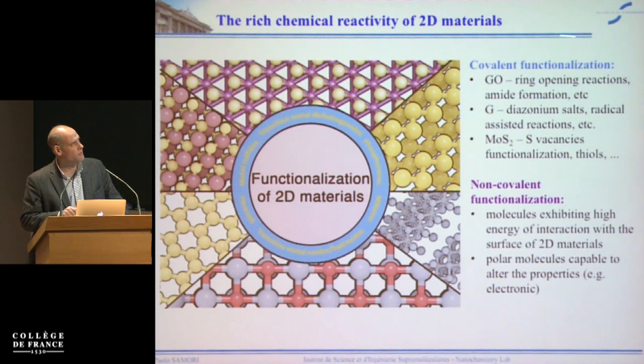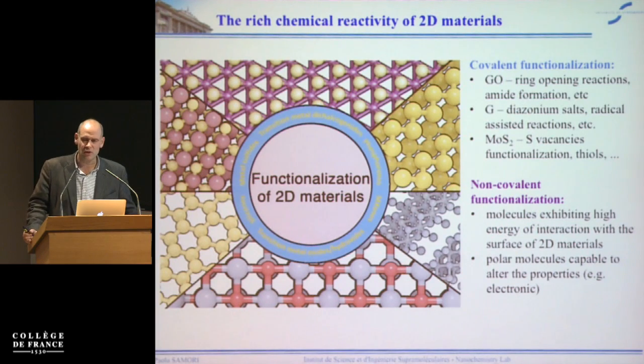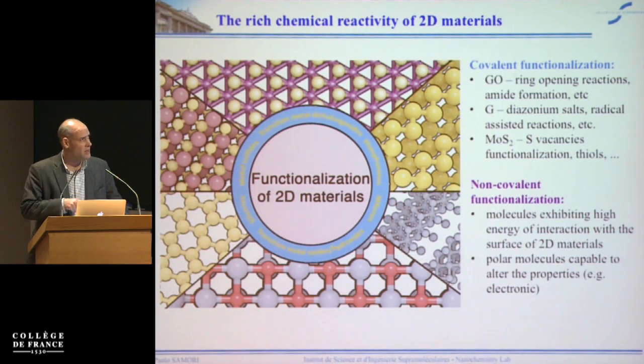And here, if you think about covalent chemistry, of course, the ring opening reaction is what you can use with GO. With graphene, the yield is a bit lower, actually, to be honest, but you can do the chemistry based on diazonium salts. And for example, if you play with molybdenum disulfide here, you can do a lot of thiol chemistry. And this is what I'm going to show you now. I will show you later how non-covalent functionalization can also be exploited.